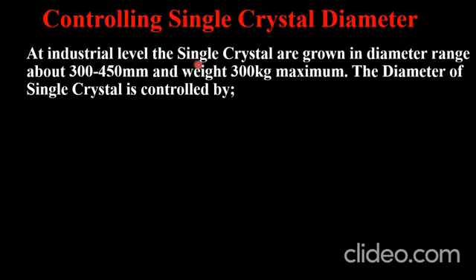Now coming to the diameter of the single crystal, how in the Czochralski technique the industrialists control the diameter of the single crystal. They need a single crystal with a specific dimension. How does the industrialist achieve a specific dimension? At industry level, single crystals are grown in a diameter range of 300 to 450 millimeter. The latest reported diameter is in the range of 450 millimeter, and the maximum weight achieved till now is around 300 kg. So how do the industrialists control this diameter and weight?